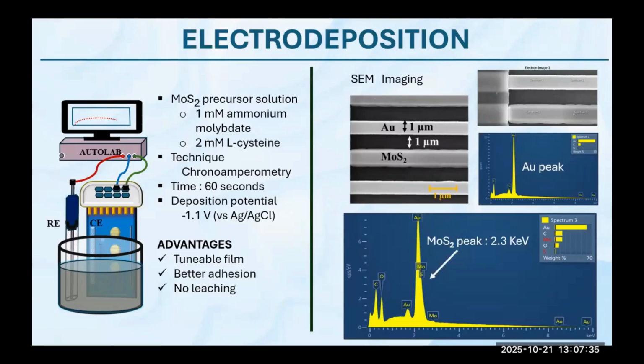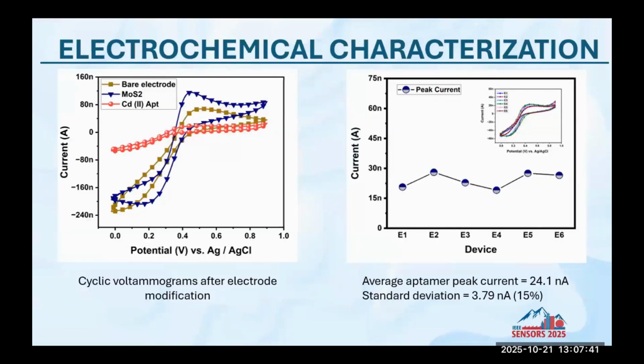Now, having confirmed that we have electrodeposited MoS2, we functionalize this electrode with a cadmium aptamer to perform the electrochemical sensing. First, we observed a change in current with the bare electrode. After depositing the MoS2, the peak current in cyclic voltammetry increases. This is because the conductivity of the electrode increases by depositing molybdenum disulfide on top of it. Further, when we modify the electrode with our aptamer, it forms subsequent layers on the material, as a result of which the conductivity decreases and the peak current is reduced at the aptamer level.